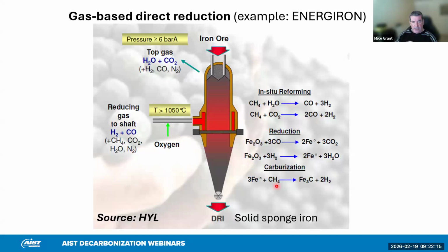Now, this is an example of gas-based direct reduction. There's two types, the Energiron here, but there's also the Midrex gas-based technology. Both of those rely on natural gas, and natural gas is reformed by reacting. Well, natural gas is mostly methane. We react it with both water, steam, and CO2 to make our reducing gas. And reducing gas is CO and hydrogen. These react with the iron oxide to produce metallic iron. You can see the two equations here. A less significant but important reaction is the carburization of the DRI itself. So in many cases, the metallic iron reacts with the natural gas itself to produce iron carbide, which provides a useful source of carbon in the DRI product for the electric arc furnace that's going to melt it afterwards.